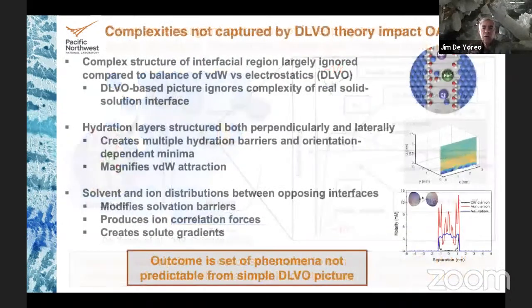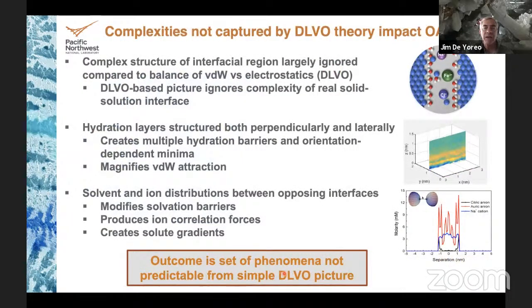The problem is that the world's far more complicated than that, and there are many complexities that aren't captured by DLVO theory that impact OA. There's the complex structure of the interfacial region, and it's largely ignored compared to the balance between van der Waals forces and electrostatics. The DLVO theory ignores the real solid-solution interface. For example, there are hydration layers that are structured both perpendicularly and laterally across the surface. And that creates multiple hydration barriers and orientation-dependent minima, and it magnifies the van der Waals term. So even the basic terms in DLVO theory are altered by this interfacial solution structure.